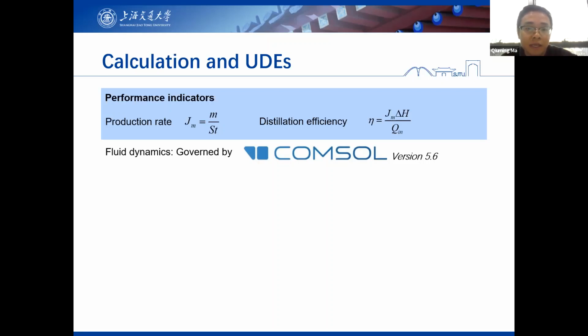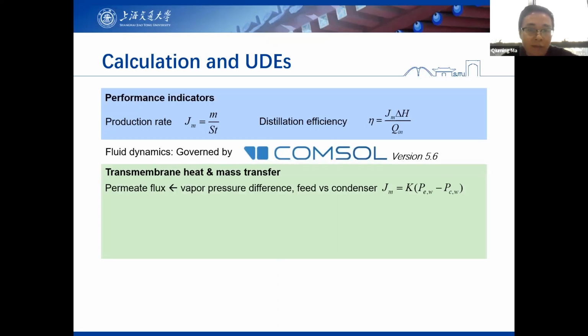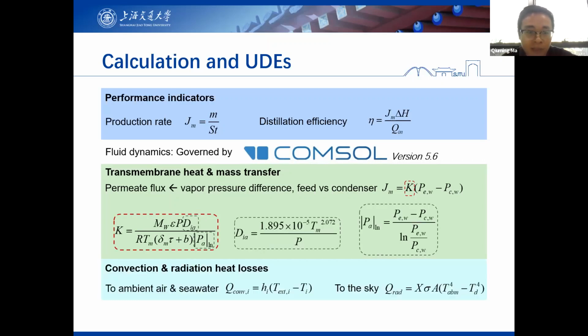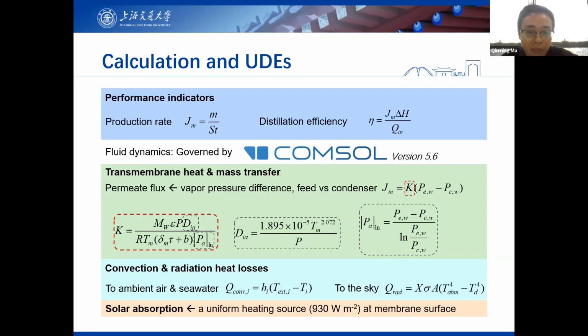For the performance indicators in our simulation, we simply use production rate, which is common, and also distillation efficiency. It's defined by the latent evaporation heat of all the production water against the solar energy income. For the fluid dynamics of the device, we just let it be governed by COMSOL. Then we insert the calculation of transmembrane heat and mass transfer, most importantly the permeate flux, using the typical equation with the calculation of the coefficients. For the losses, we consider the convection and radiation heat losses. And last, as mentioned above, we consider the solar absorption as a uniform heating source at 930 watt per square meter at the photothermal membrane surface, actually.